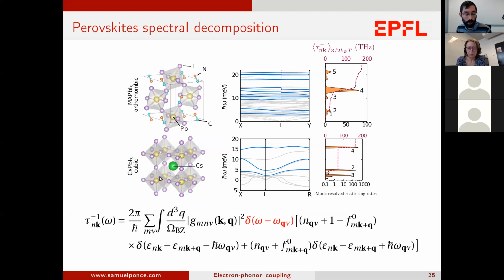So when we try to simulate MAPI, what we do as an approximation is to use cesium lead iodide, and then we just use the lattice parameter of MAPI. This is a, let's say, brutal approximation, but at least we are spherically symmetric, and so we are recovering the sort of average. But we know that, of course, it's not cubic. It appears to be cubic on the XRD simply because of the average over all the motion, but at each given time, of course, it's not cubic.